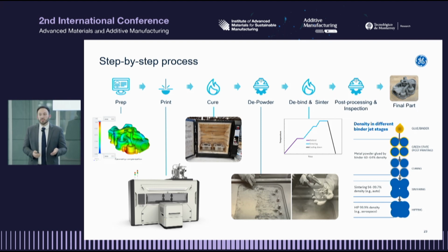Up to 80–90% of the melting temperature, that lets the kinetics take over, and then you have atomic motion across the surface of powder particles, and you get shrinkage on the order of 20 to 30% on a linear basis across a component. So in binder jet, it's easy to say we can print anything. Like, it's really easy to print stuff in binder jet. With 600 or 900 dots per inch on the print heads, you can resolve a lot of components. The question is, do those thin walls or that structure survive through the sinter cycle? So that's why we spend a lot of time optimizing our debind and sinter with the proprietary binder system that belongs to GE.